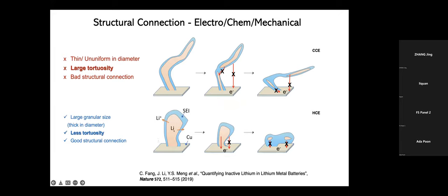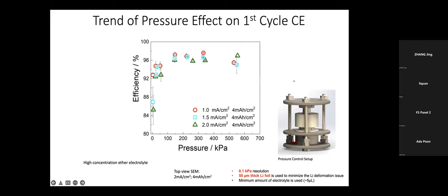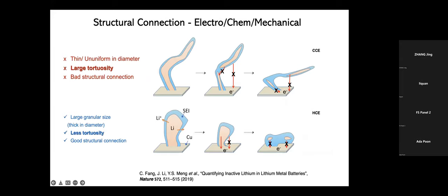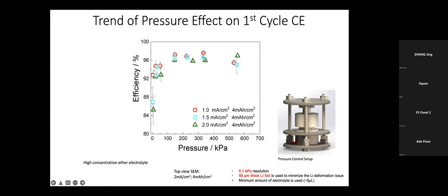Now, if I use the simple schematics to show you why you wanted to have this kind of dense, large particles of lithium metal, I think the story is quite self-explanatory, right? Because the SEI, the blue portion, is electronically insulating. So if you have this type of elongated particles, you always run into the problems of having a large amount of lithium trapped inside. Of course, you can put on pressure. We showcase that the pressure is so important that you can imagine if you put the pressure and push those lithium towards the SEI, you get a better Coulombic efficiency.